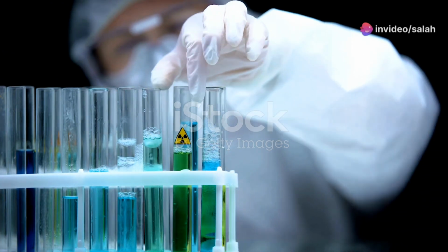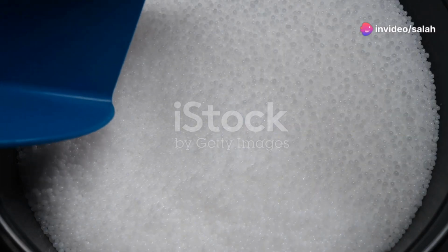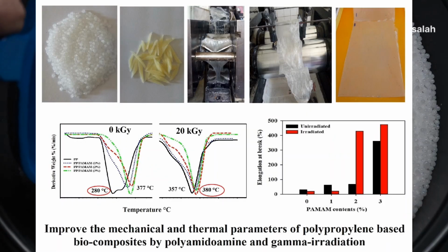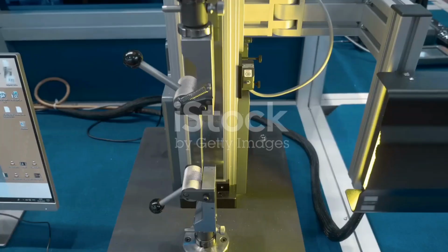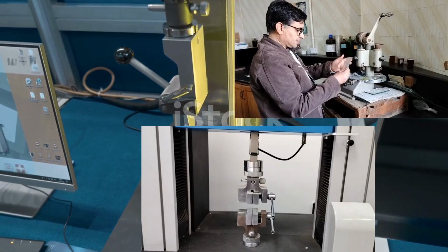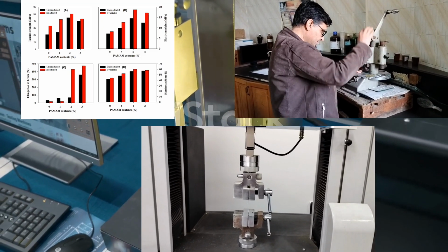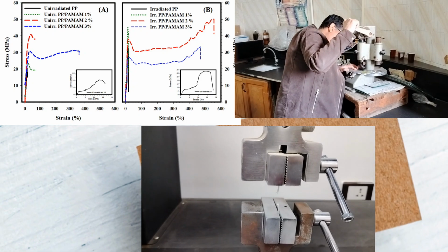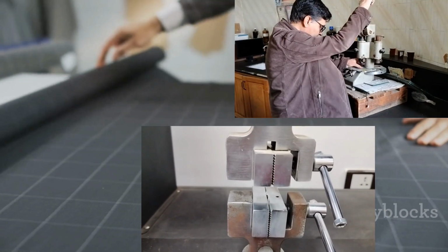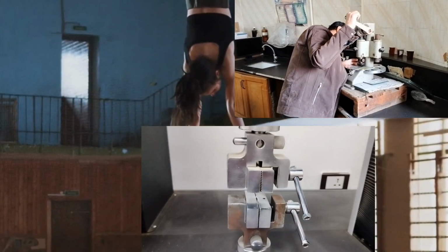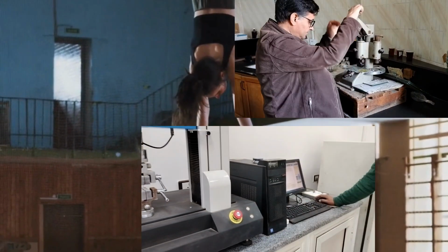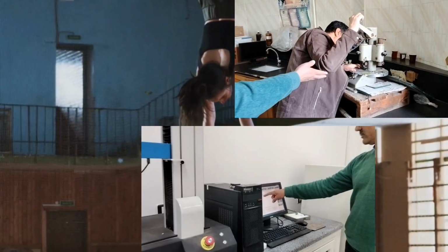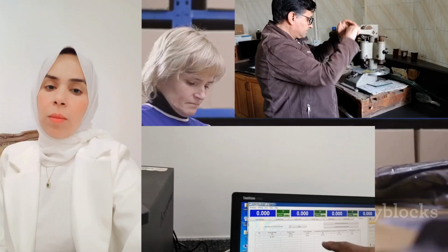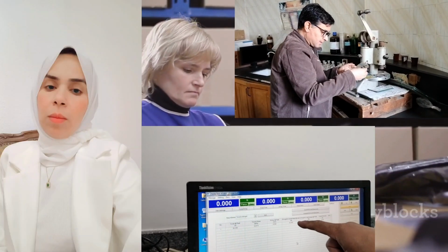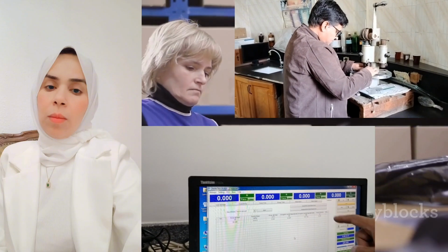The incorporation of natural fibers and the application of gamma irradiation yield remarkable improvements in the mechanical properties of polypropylene biocomposites. Tests have shown that these materials exhibit significantly higher tensile strength, meaning they can withstand greater pulling forces before breaking. This enhanced strength translates into more durable packaging that can protect its contents more effectively. Moreover, the biocomposites demonstrate increased flexural strength, indicating their ability to resist bending and breaking under pressure.